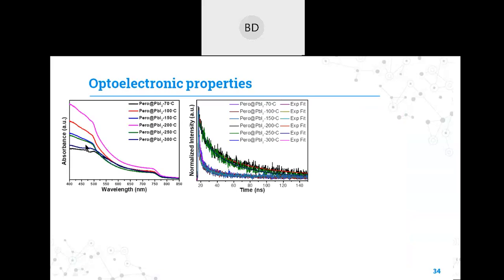If you see the absorption here, the perovskite which is at 70 degrees centigrade shows a little less absorbance. By using the 200 degree annealed lead iodide, the absorbance in the perovskite has been improved due to improved surface coverage in the perovskite film. And the lifetime of the charge carriers in the perovskite has been improved significantly. We have observed almost a 10 times increase in the perovskite lifetime when you use the lead iodide film annealed at 200 degrees centigrade.